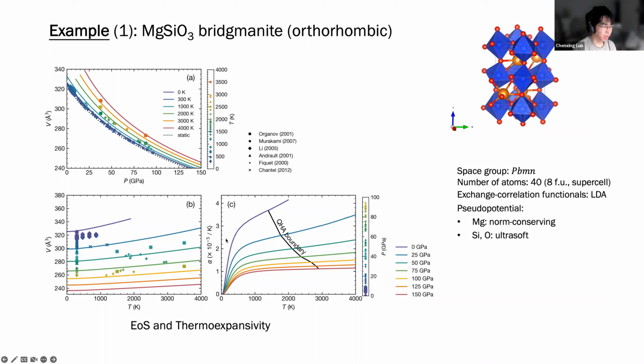On the bottom right, this is the expansion coefficient. This boundary is calculated using the second order derivative of the expansion coefficient as a function of temperature, which defines where the quasi-harmonic approximation is valid. So the quasi-harmonic approximation is basically valid below this temperature range.